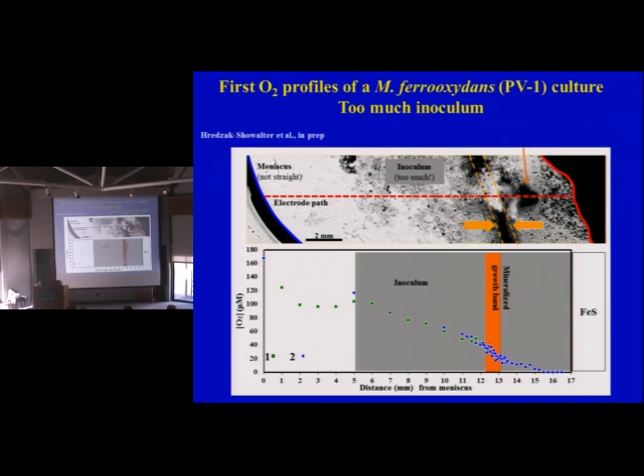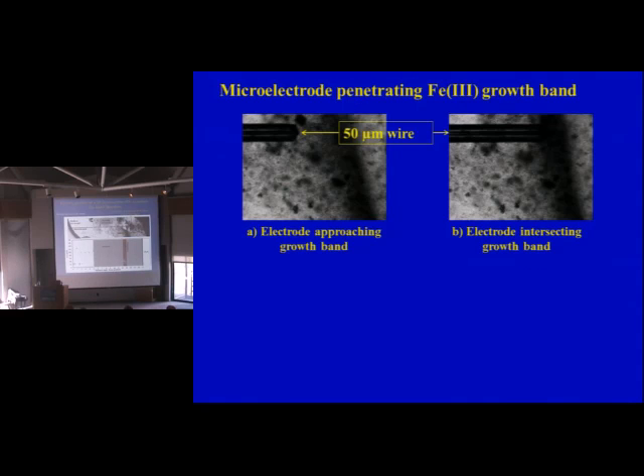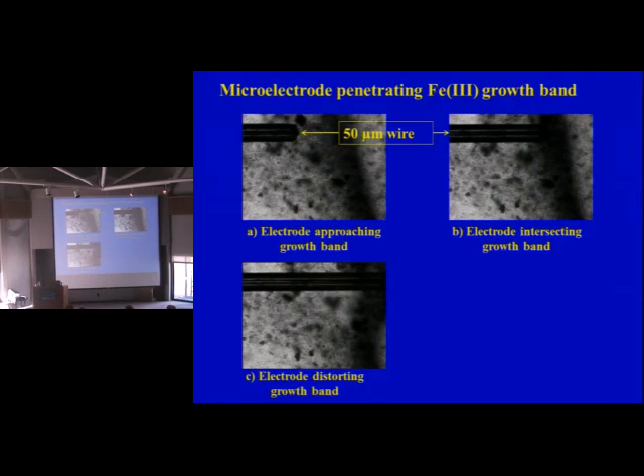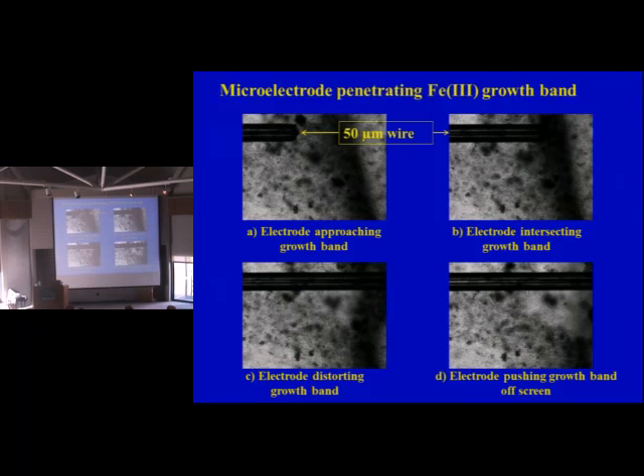Now, it turns out because the inoculum was so much, we produced so much iron oxide, we got a really thick growth band. And as the electrode went through, it pushed the iron oxides away. So just for kicks, let's show you that. Here's the tip of the electrode approaching. Here it is reaching the band. And here it is penetrating right through the band. Okay? And all the way through. So this is what happens when you have too much inoculum.